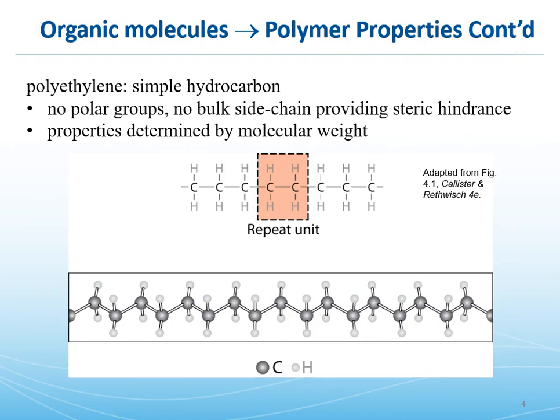When something physically gets in the way of something else, when we're talking about molecular level interactions or chemical reactions, the word that refers to that is steric hindrance. You can think about it as just hindering, getting in the way of something. And from the standpoint of polymers, what you're usually getting in the way of is some kind of secondary bond between chains wanting to lie side by side, or a chain folding over and laying back across itself, which is how polymers crystallize.